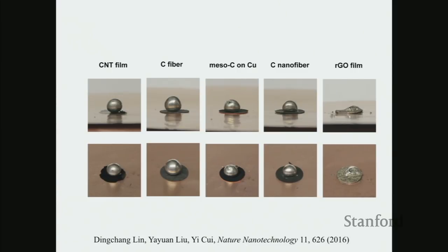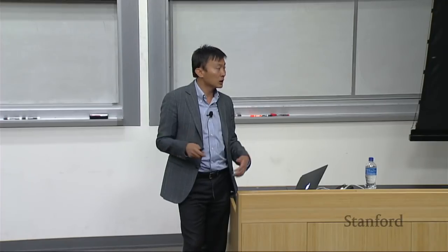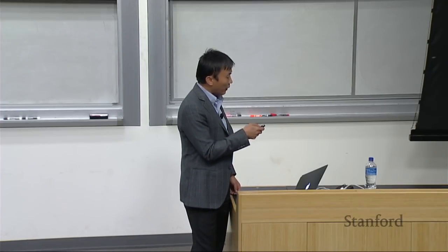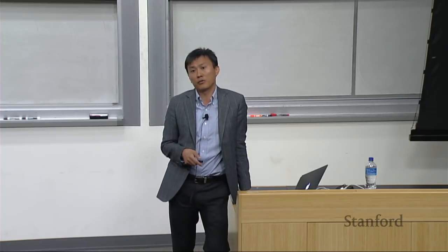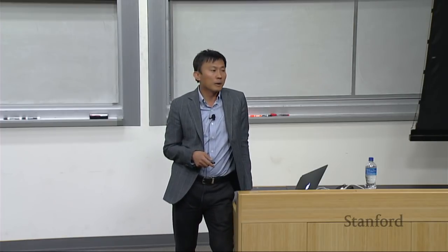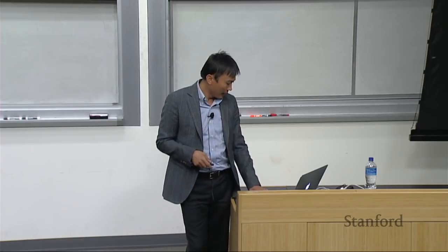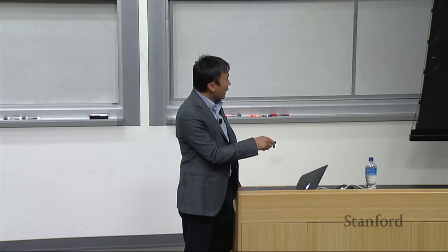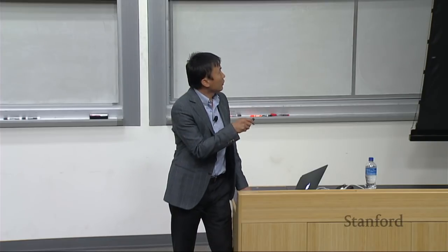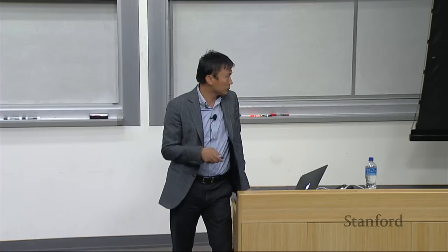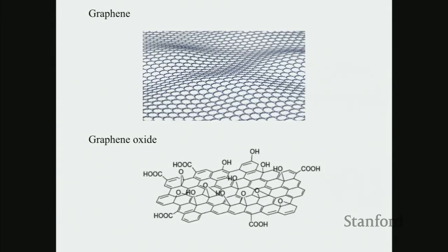So we recognize, similar to water, where we have hydrophobic and hydrophilic to describe whether water can wet a surface or not, now we invented a new term. We call this lithophobic or lithophilic to describe the lithium wetting behavior. The reason graphene oxide can wet is this polar functional group of OH, COOH. Compared to graphene or regular carbon, you don't have enough of this polar group. The polar group will react with lithium.